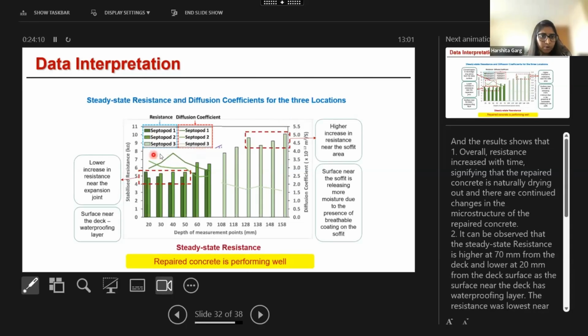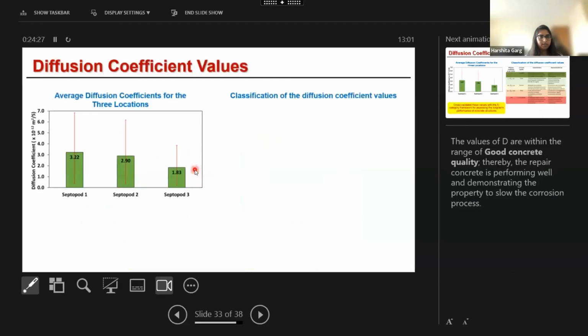If you look at the diffusion coefficient values, it is higher near the expansion joint, indicating that contamination in the bridge may arrive from the deck surface. But overall, it was performing well. So now these diffusion coefficient values were averaged for each septopod. And here we can see the 3 values.